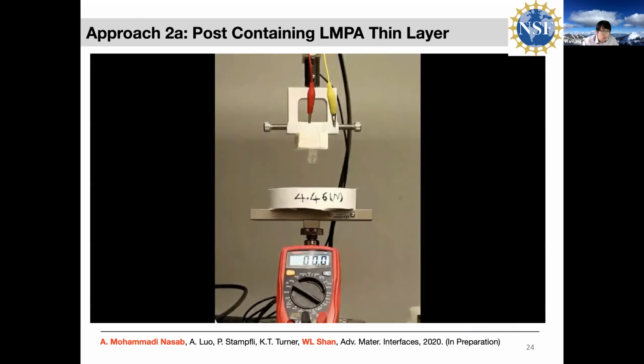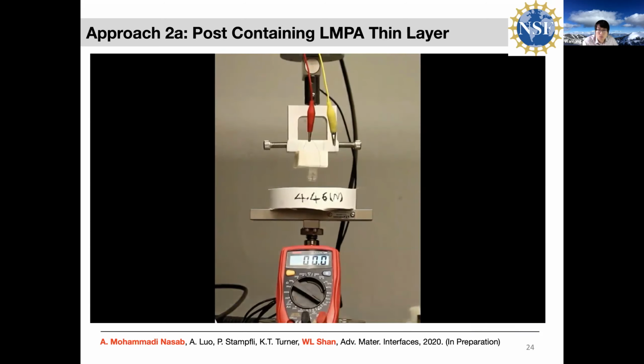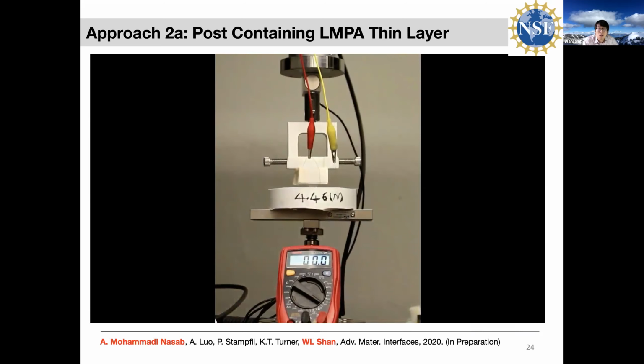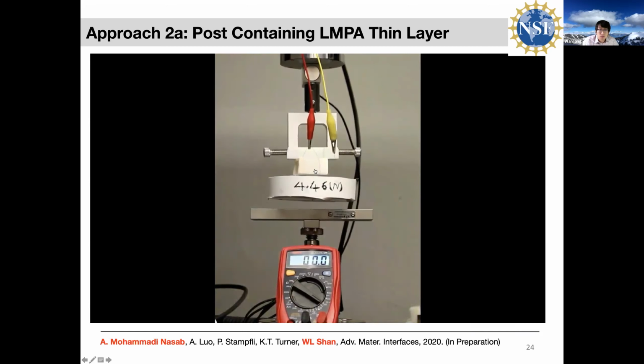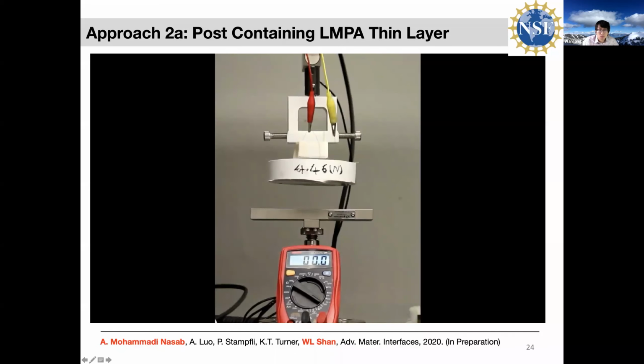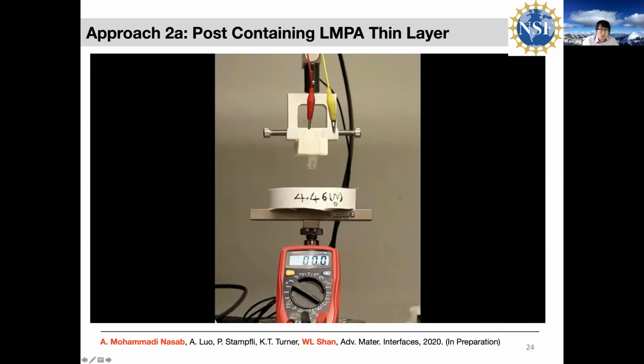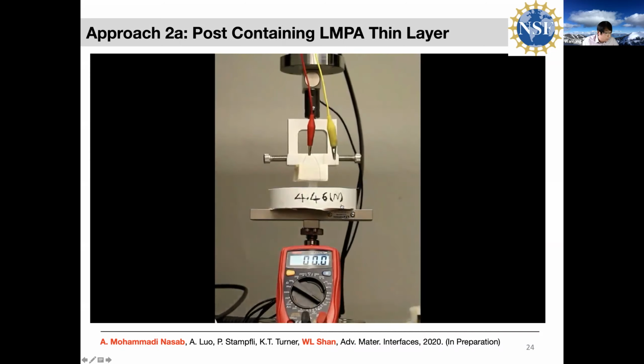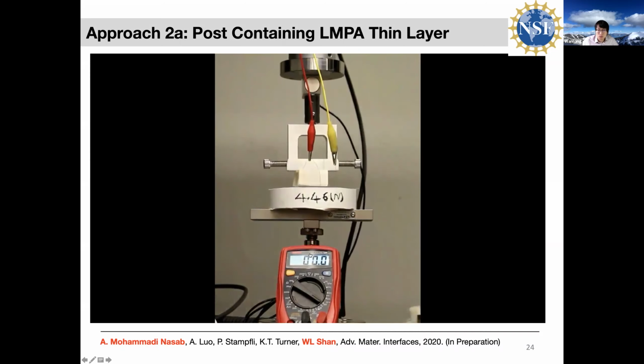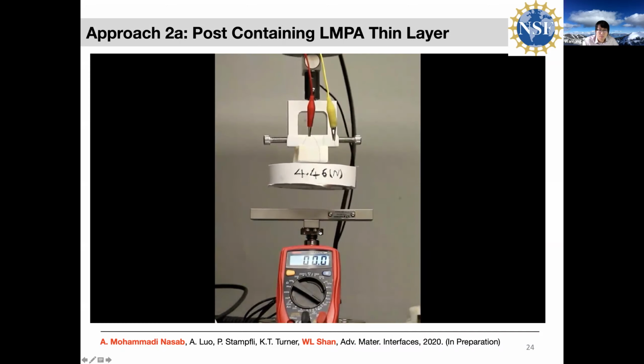Anyway, I won't go into details about this, but I do have a quick video to show it. This is real time. Here we have a block of aluminum disc. You can see that with this small piece of elastomer, we're able to pick up this almost 1 pound aluminum disc, and we apply 5 volts for roughly 1 second. Between 1 and 2 seconds, we are able to release this object, and this is real time. So with this approach, we can reduce the voltage required, which will make everything portable. And we can also reduce the time, which makes it more practical in a factory.